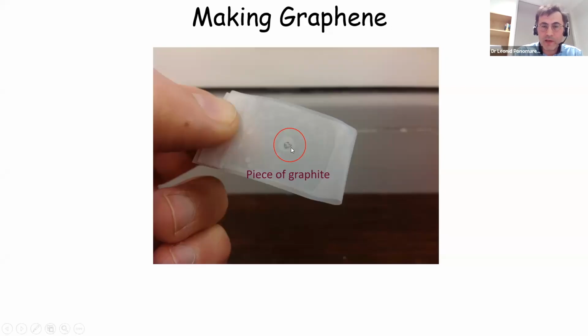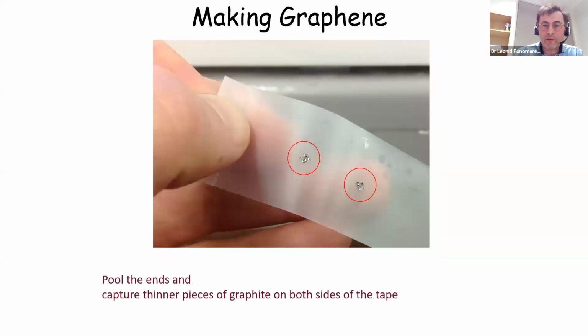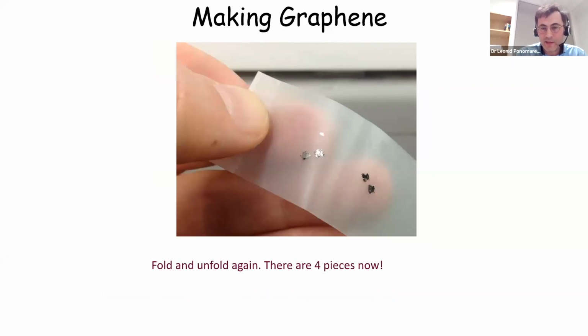Here we have a Scotch tape, and between sticky layers of Scotch tape, we have a graphite crystal in this red circle. Now if we pull the two ends of the Scotch tape, then this graphite crystal will split in two. This is again because the attracting force between layers is very, very small, so it's very easy to break. Now we can fold this Scotch tape again, but not exactly along the same line as it was folded initially, and pull the ends again. In this case, each crystal, so we had two of them, will split again in two. Now we have 4 different crystals, and we can repeat this process again and again, and every time a crystal will be thinner and thinner.